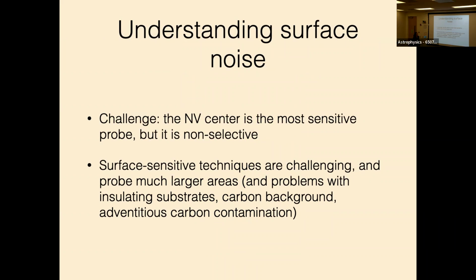One of the challenges is that the NV center is a very sensitive probe, but in some sense it's very non-selective. It's basically going to tell you, I have a long coherence time or I have a short coherence time. It doesn't really give you any clues about the microscopic mechanisms of this noise. There exist ways to study the surface directly, like surface-sensitive spectroscopy, but in general these techniques are quite challenging, and maybe more fundamentally, they probe much larger areas than what the NV center is looking at, and they have very low sensitivity. So it's not actually obvious right off the bat that you're going to learn information that's relevant for the surface noise that dominates NV decoherence.